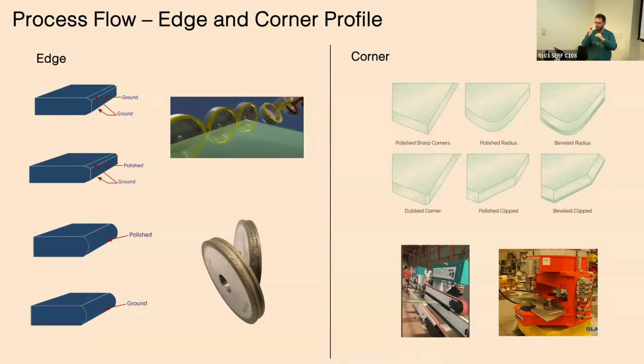You put in a curve and a curve, but when they end up at 90 degrees, unless you surface profile the whole thing with a cam and follow CNC, you don't finish that edge. So it's a bit non-controlled. You end up with a little chip there or a sharp corner, which we'll talk about later. When you thermally temper, it's a little bit scary when you end up with sharp corners.